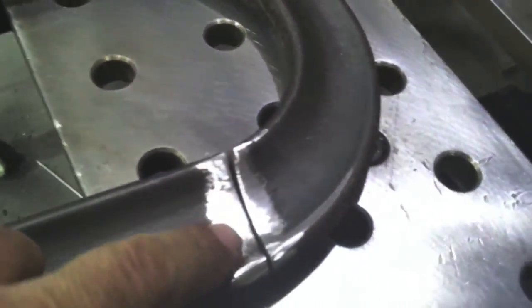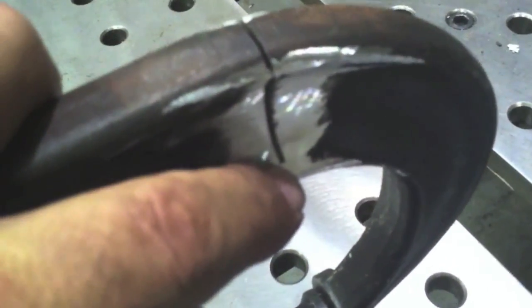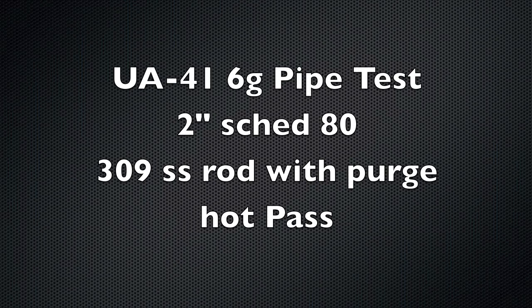Another example would be this C-clamp - a nice C-clamp that somebody accidentally left clamped on material and almost sawed all the way through it on the bandsaw. So, throw away a fifty dollar or higher C-clamp, or weld it up? I couldn't really identify the material type. I didn't want to call the manufacturer. I spark tested it, did a little puddle on the edge to see if the metal would harden, tried to file it, and it didn't really seem to want to harden much. So I figured, well, I know 309 is going to work. And it did. That C-clamp is running right now, still clamping, still working, doing fine. Didn't give me any trouble at all. I did several passes on that to build up the thickness.